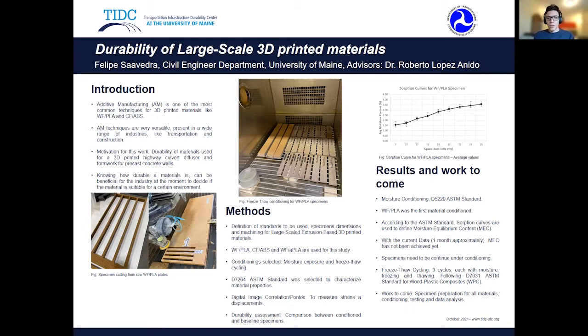Wood flour PLA, carbon fiber reinforced ABS, and wood flour aPLA are the materials used in this study. The difference between the two PLAs is that the wood flour aPLA has some features that solve some issues that the first wood flour PLA has, the most important one being related to shrinkage at the time of printing. Once the material and the form are printed, they tend to shrink. So some dimensions of the materials and the form need to be bigger to compensate for this. So it's going to be really interesting for this research work to see how the two PLAs behave.